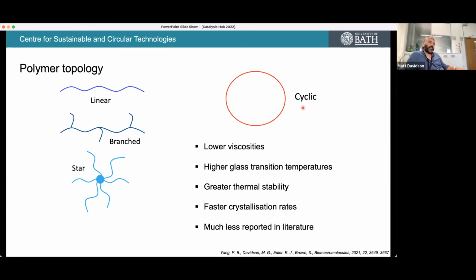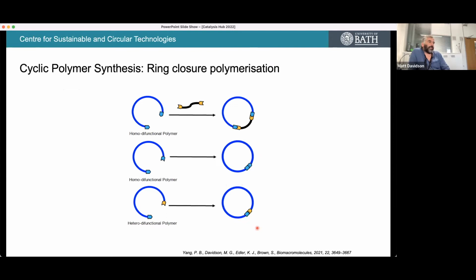But if you can make a pure cyclic polymer, one that's not significantly contaminated with linear components, the properties are really interesting. They have lower viscosities, and that might make processing of a particular polymer useful. They have higher glass transition temperatures and greater thermal stability because they don't have chain ends, which can lead to thermal instability. And they potentially have faster crystallization rates, but they are significantly less reported in the literature. The main reason for that is that they aren't very easy to make, at least not very easy to make pure and uncontaminated.